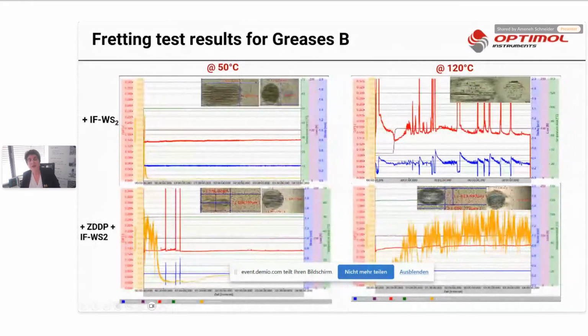A very interesting formulation is the grease B, naphthenic polyalpha olefin, with this special nanoparticle. It works fantastic at 50 degrees Celsius due to different tribochemistry. I won't go through that in detail, but you can see here a very constant friction value and very low, or constant, electrical contact resistance. We destroy all this protection at 120 degrees. There is no protecting film at this temperature.